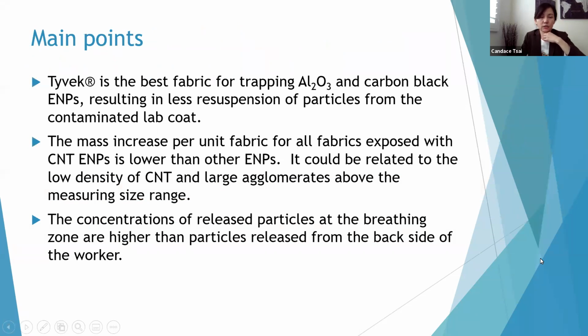Okay, so to summarize this, we found Tyvek is still the best fabric for trapping aluminum oxide. Remember, I showed you the mass change per unit mass of fabric is very high. High means the particle being trapped onto the fabric - they didn't get released out, and it's consistent with what we found from real-time particle monitoring - the release from Tyvek is pretty low. So it comes up with very low resuspension of particle from the contaminated lab coat.